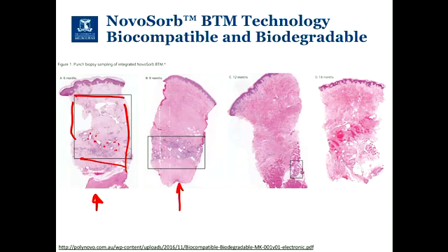After 9 months, you have a lot of tissue up the top, and there's a little bit still remaining, still quite purple, still a few little holes, and it looks like those holes are more towards the centre of where the scaffold is. So how long does it take the cells to migrate in through the scaffold? After 12 months, it's tiny, and after 18 months, it's not there.